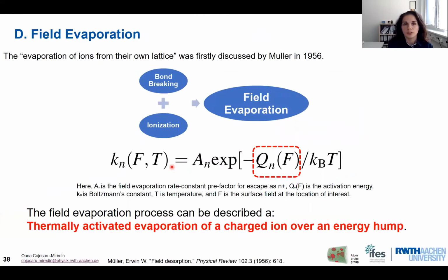So if we recall now the field evaporation process, this is simply a thermally activated evaporation process of a charged ion over an energy hump. And if we want to describe the field evaporation rate, this is simply an Arrhenius model where Q and F represent the activation energy. So this activation energy is actually the energy necessary to break the bond and to ionize the atom released, and then to field evaporate this atom as an ion.